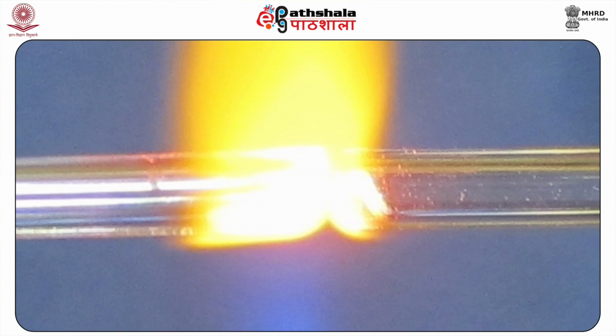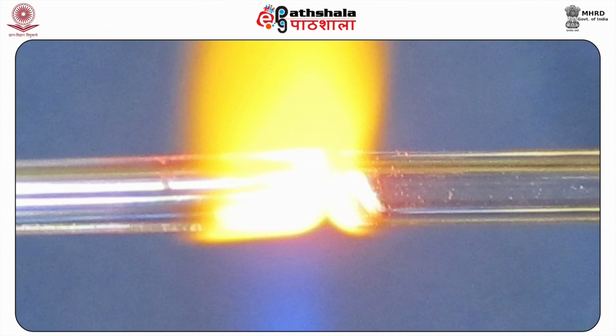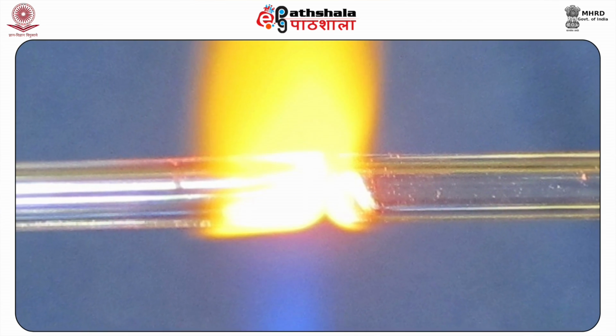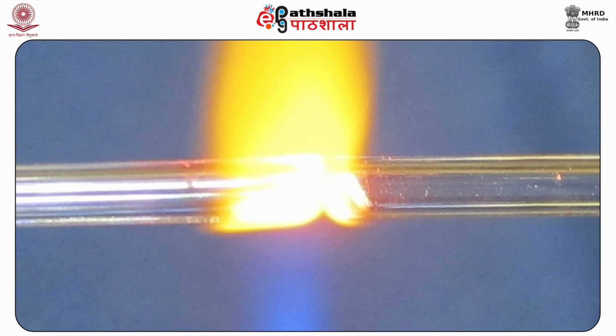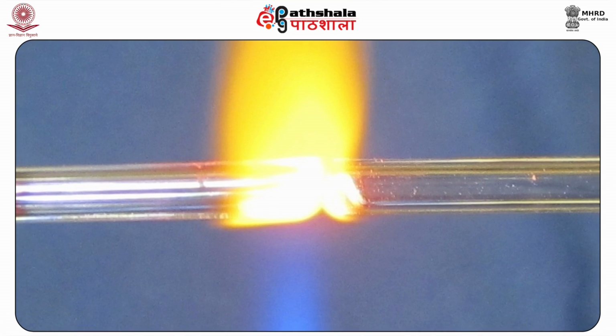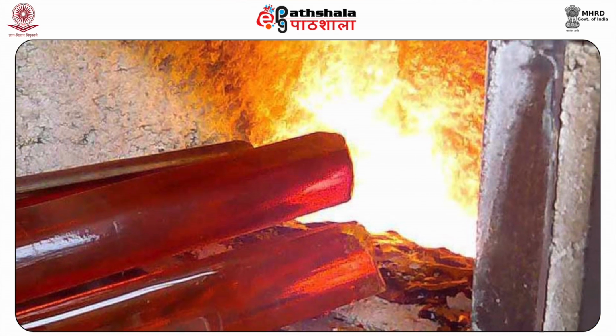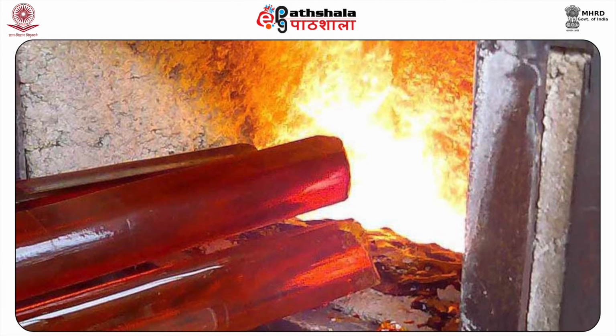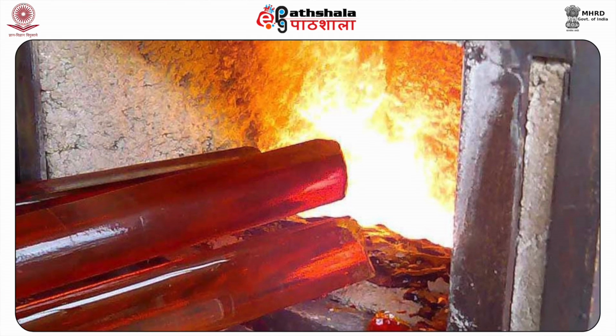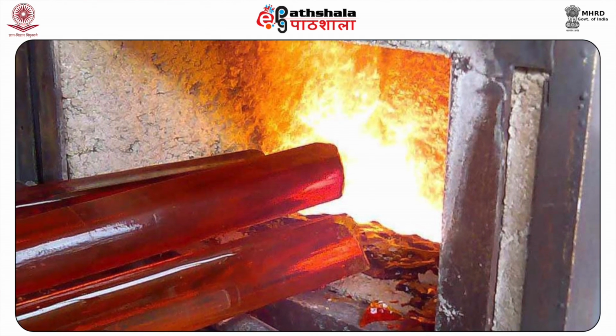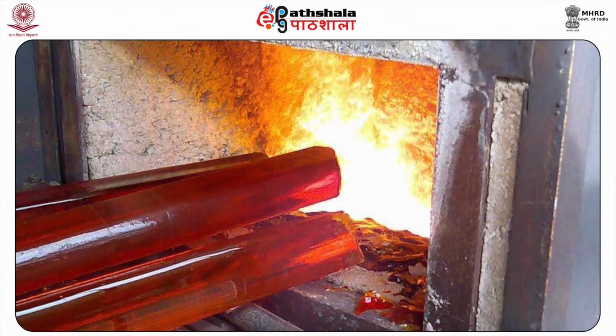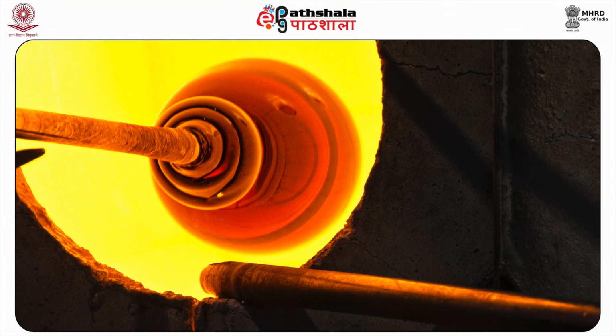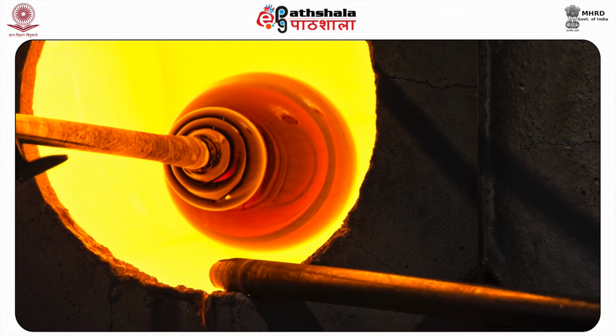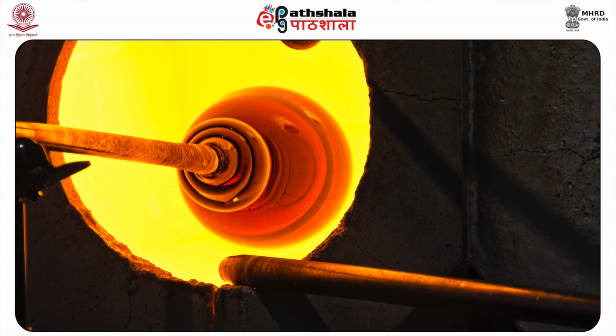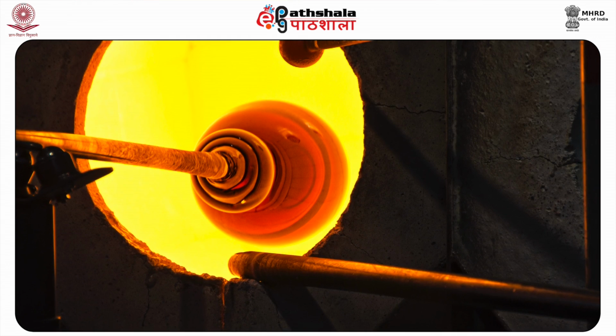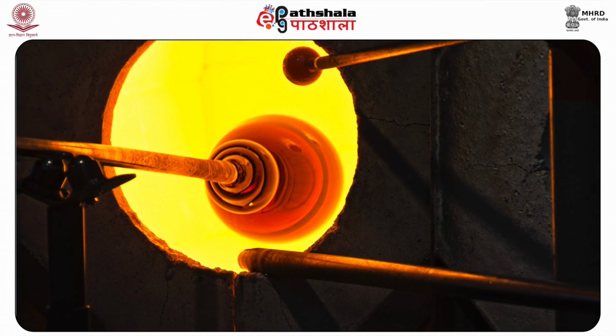In order to increase the rigidity of the molten glass and to expedite the blowing, a refined change in the composition of glass was made. Fisher and McCrae postulated that a lower concentration of natron, which acts as a flux in the manufacturing of glass, makes the glass stiffer for blowing. When the glass is blown, the thin layers are more viscous than the thick layers because the former cool faster than the thick ones.